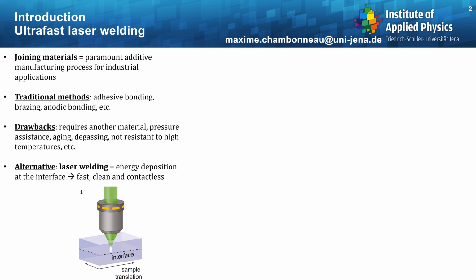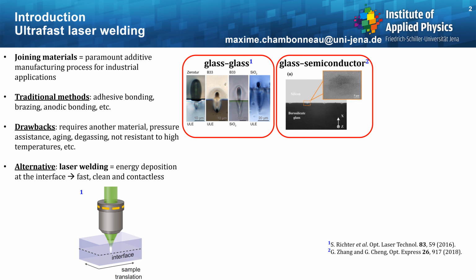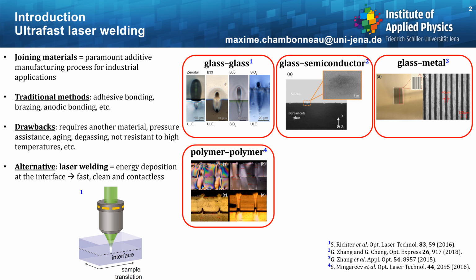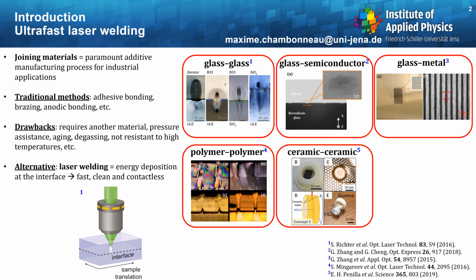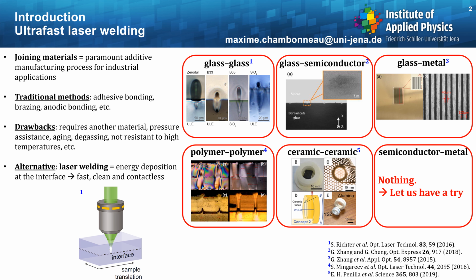As a very nice alternative, the laser welding technique has been developed. It consists of energy deposition at the interface and provides a fast, clean, and contactless way to join two materials. Noteworthy, it has been shown to be applicable in different material configurations such as glass-glass, glass-semiconductor, glass-metal, polymer-polymer, and more recently, ceramic-ceramic. However, in the semiconductor metal configuration, there is nothing too convincing so far. So let us have a try.